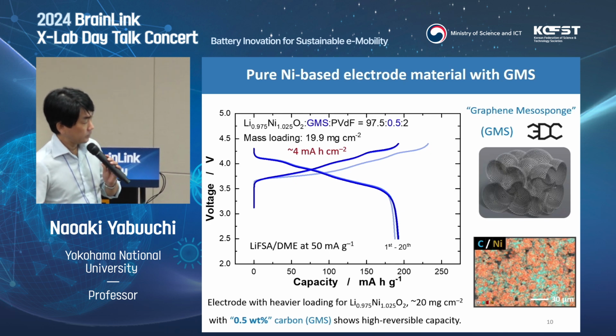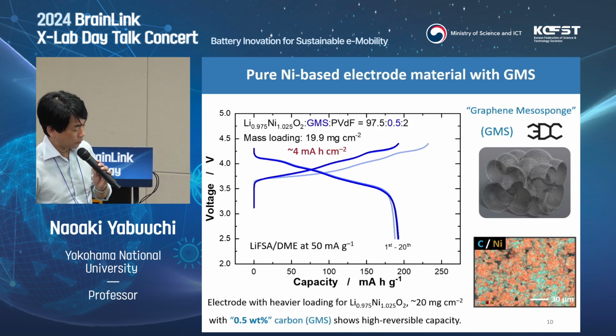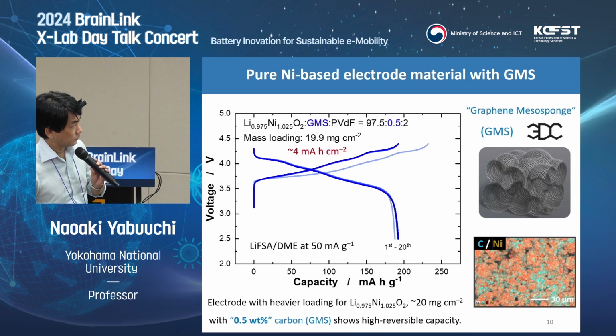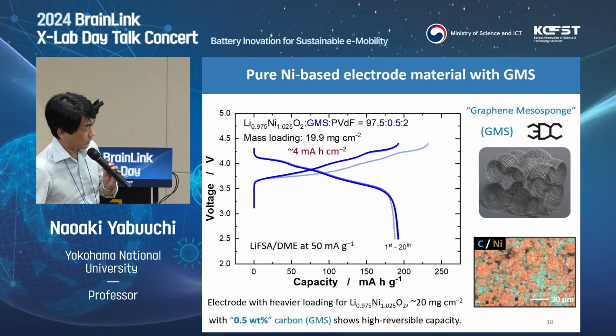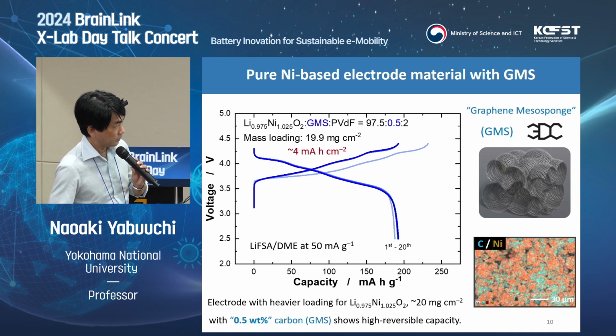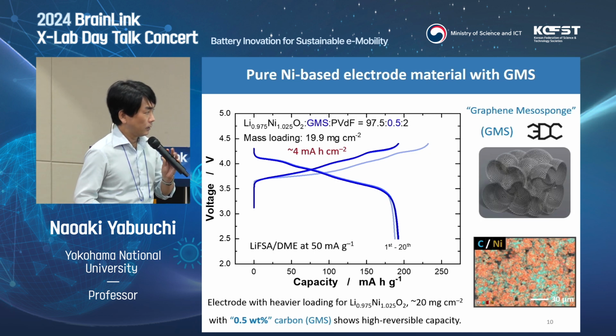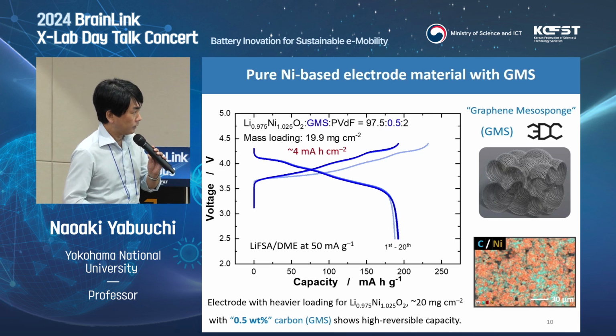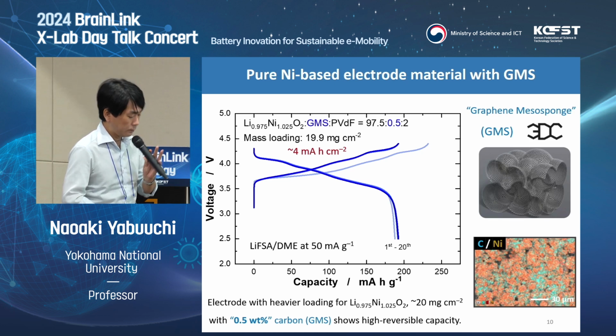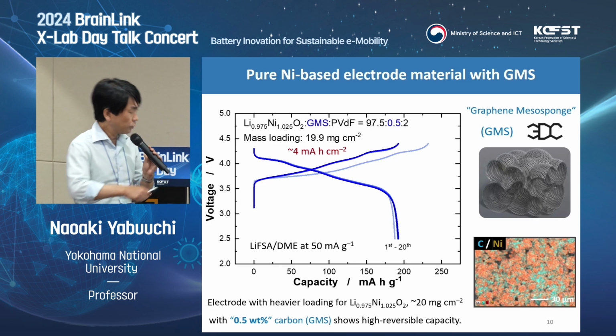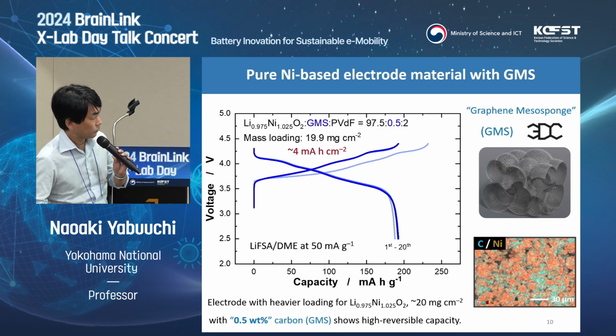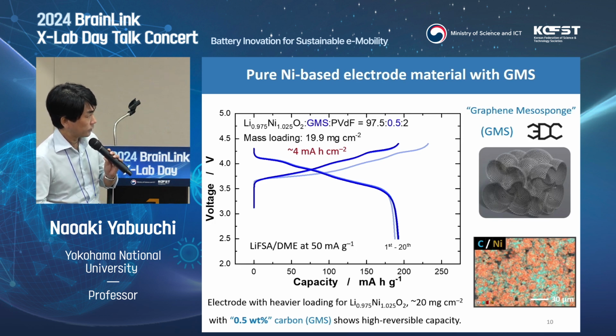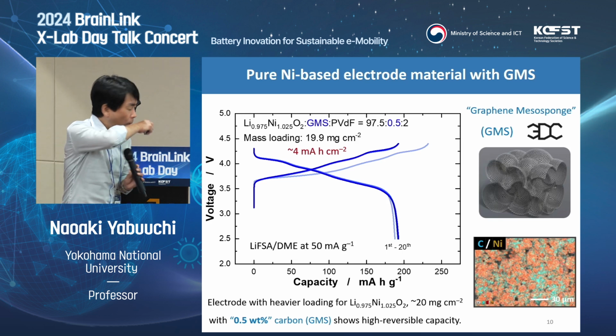And also we have very special carbon supplied by our collaborator 3DC, the so-called graphene mesosponge. This is a porous carbon with very thin graphene layers. So this sample's electric conductivity is very high, and porosity is also very high. So we can reduce the amount of additional carbon. Now we can add only 0.5% conductive carbon in our lithium nickel samples with 2% binder, so 97% active material loading.